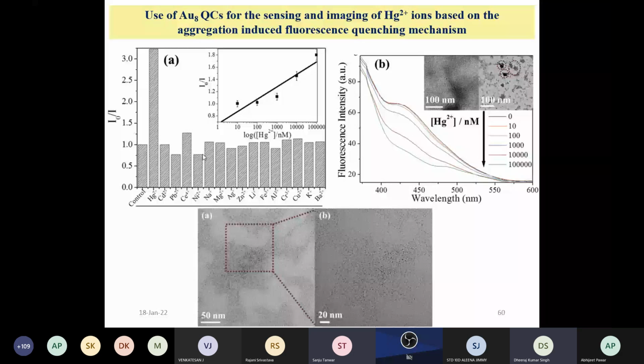Out of these 25 metal ions, only mercury was sensed. It means it will always sense mercury at a particular surface or at nanomolar concentration. If mercury ions are there and you put in gold 8 quantum clusters, your blue fluorescence color property will be quenched, and other metal ions will not affect the fluorescence property of that gold 8 quantum cluster. You have to find out selective and sensitive detection by changing the concentration, and we found that down to 2 nanomolar concentration can be sensed by this gold 8 quantum cluster.